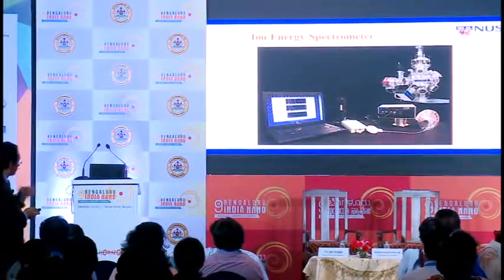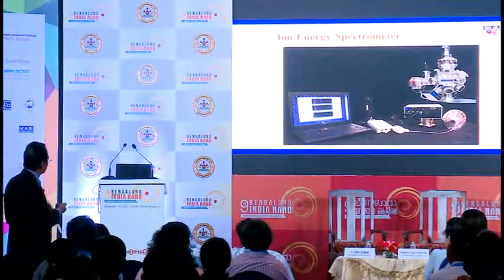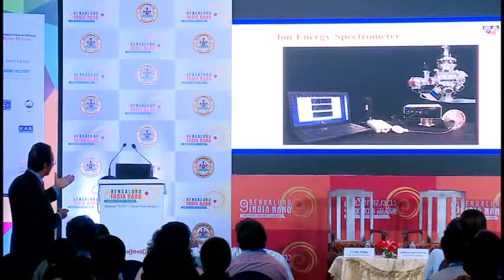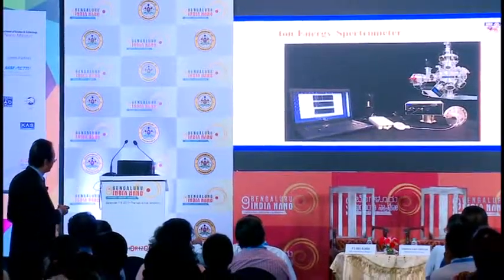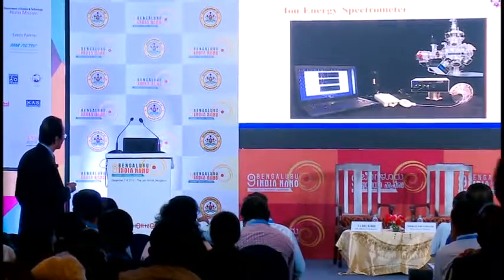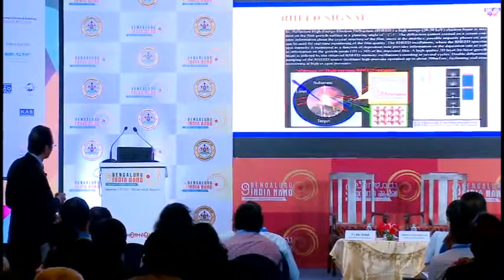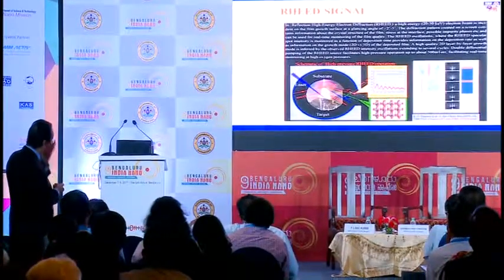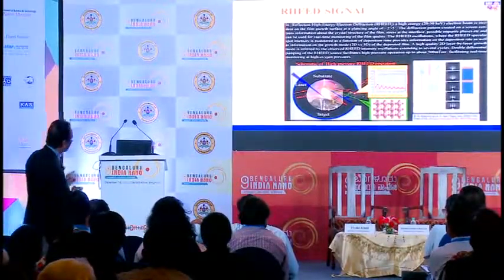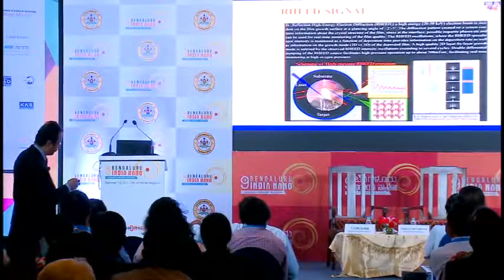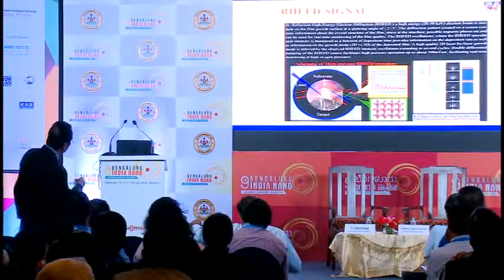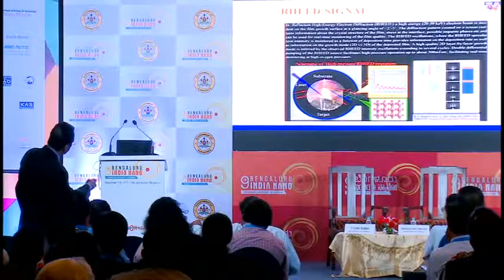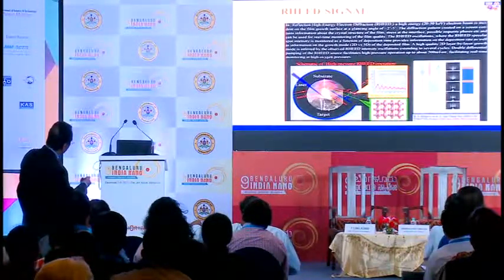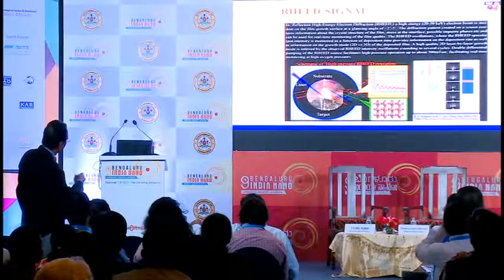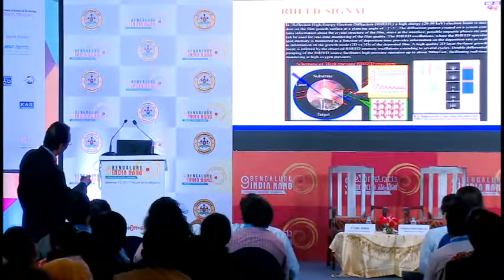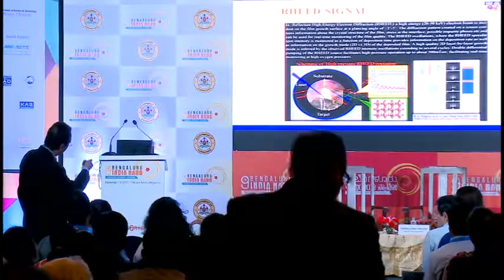Now the big emphasis in PLD today is in diagnostics. We are working on ion energy spectrometers, which can measure the ion energy in the plume, which is very important for determining the quality of the film that we're making. Then, to measure the crystallinity and the actual lattice constant, we use reflection high energy electron diffraction. You can see this grid, you essentially have a beam coming into the system, which is an electron beam, which bounces off of the substrate, and then this electron diffracts, and we can actually measure these oscillations, which are shown in red there.